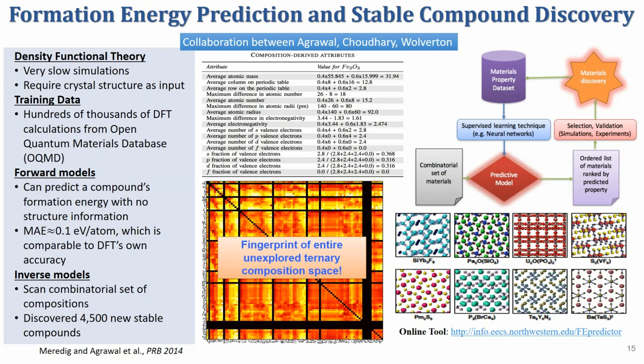I should mention the model accuracy was about 0.1 electron volt per atom, which is kind of on par with DFT's own accuracy compared to experiment, which means that with this model you can, in the worst case, go twice as bad. In the best case, you can come back to the truth. Of course, there are extreme cases, but it was kind of encouraging to see that the accuracy is of the same order.